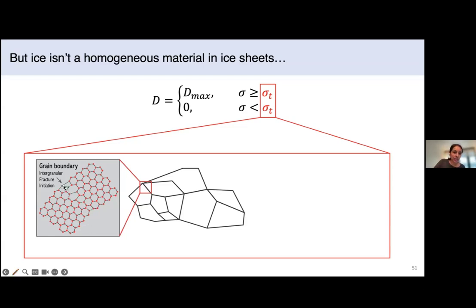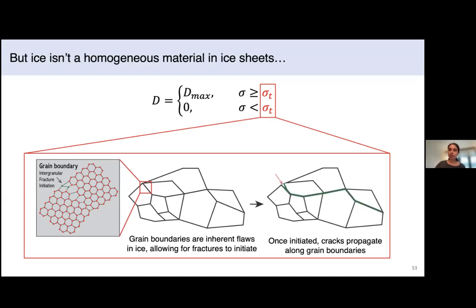But you can see, denoted by these green bonds here, that the bonds within a grain boundary are pretty weak. They're very irregular. What that means is that the grain boundaries are the inherent flaws in ice that allow fractures to initiate. If we were to stress a sample of ice, we would expect that a fracture would open up along a grain boundary, because that's where the weakest bonds are. And if we were to continue to stress that sample, we would expect those cracks to continue to propagate along grain boundaries.